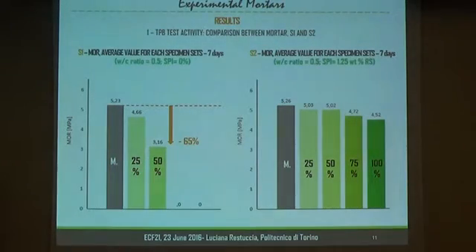From the TPB test activity, we obtain that, for example, in series 1, in which there is no addition of superplasticizer, as you can see in the histograms, we obtain a huge decrease in terms of modulus of rupture. And you can see that over 50% of replacement, there is the impossibility to cast the mortars. For this reason, in series 2, we decide to add the superplasticizer